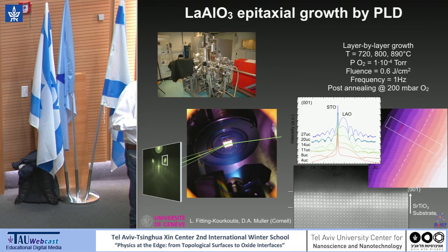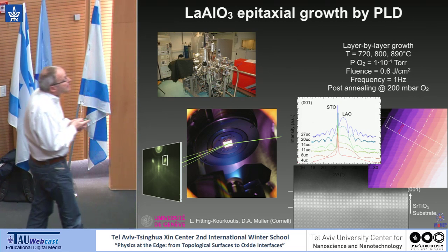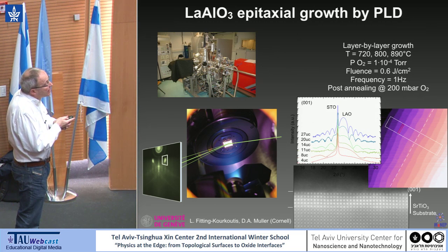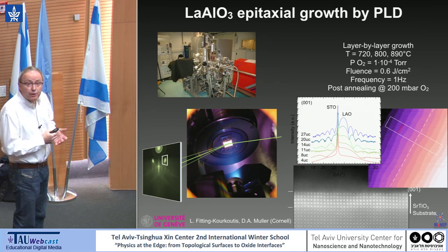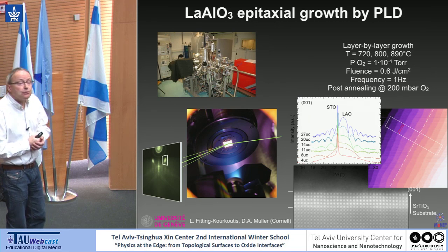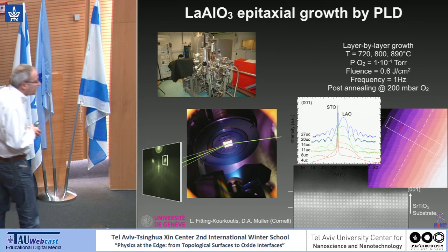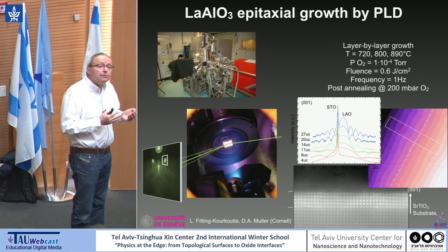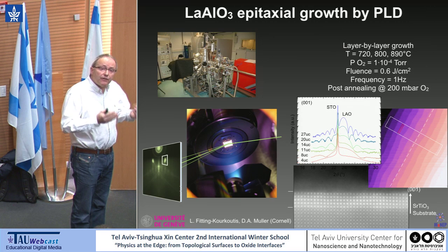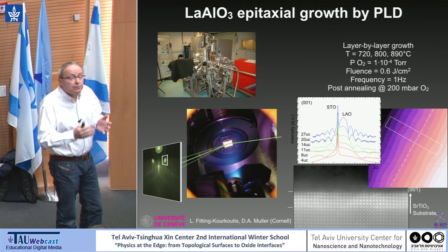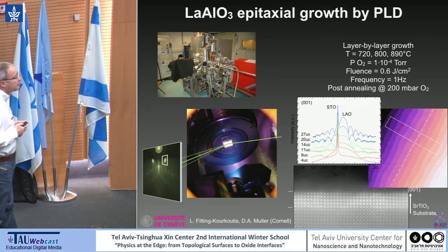And so to avoid as much as possible oxygen vacancies, after the deposition at high temperature, we introduce 200 millibar, very high pressure of oxygen, and we let the sample cool in oxygen. This is maybe a little bit technical, but it allows very good reproducibility from sample to sample to be obtained.